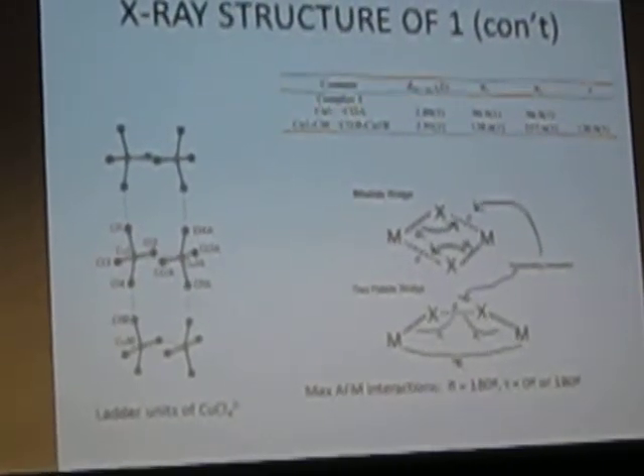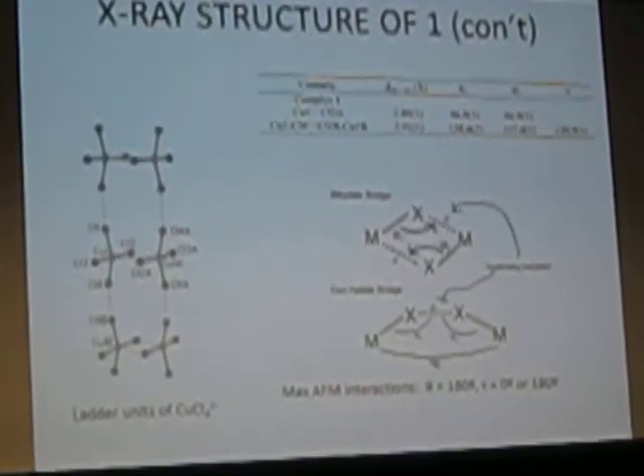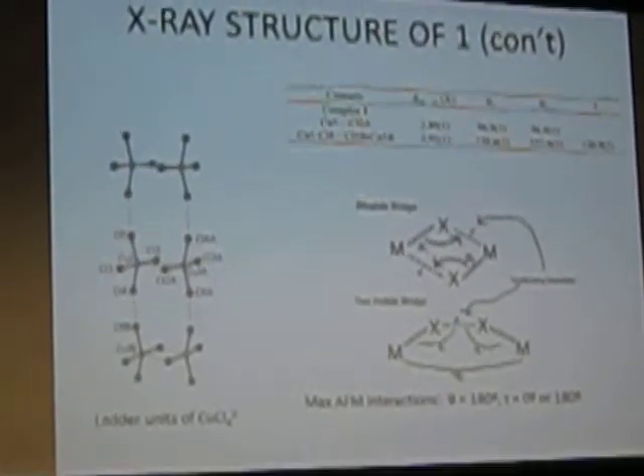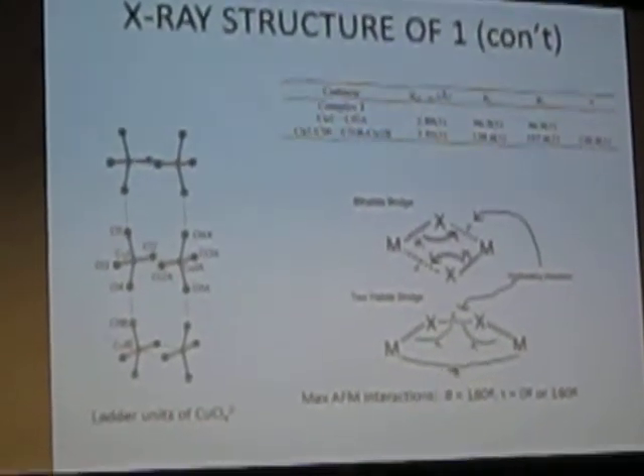This is the most interesting part, actually. So this is where the magnetic species lie. This is where the copper lies. So how do these actually arrange themselves? Well, they dimerize, and the dimers stack along the b-axis of the crystal. So the distance between the two units in a dimer is about 2.9 angstroms, and then the distance between the dimers along the b-axis is about 3.9 angstroms, so a little bit longer. So we expect a little bit stronger exchange between the two units in the dimer than across the dimers here.